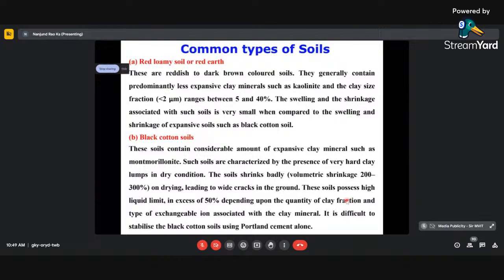The second is, as you go to the north of Karnataka, you will see black cotton soil. It is good for agriculture, particularly cotton, groundnut and other agricultural products. But these soils contain a considerable amount of expansive clay mineral, what I already mentioned, montmorillonite. Such soils are characterized by the presence of very hard clay lumps in dry condition. The soil shrinks badly, with volumetric shrinkage of something like 200 to 300% on drying, leading to wide cracks in the ground. These soils possess a high liquid limit in excess of 50%, depending upon the quantity of clay fraction and the type of exchangeable ion associated with the clay mineral. It is difficult to stabilize black cotton soils even by using Portland cement or lime alone.